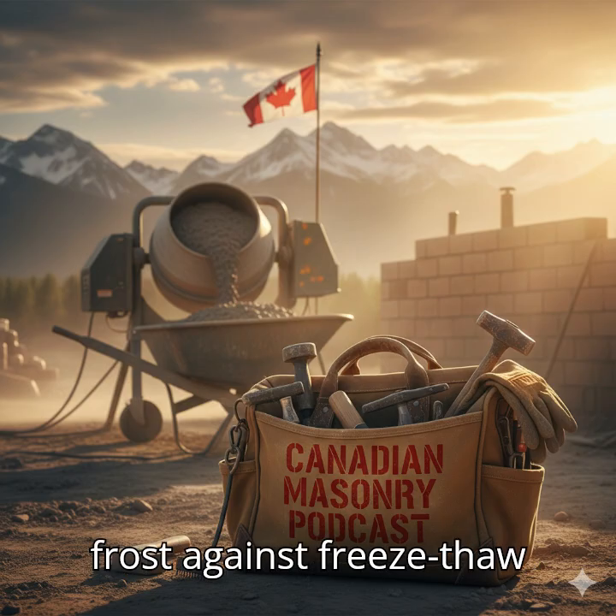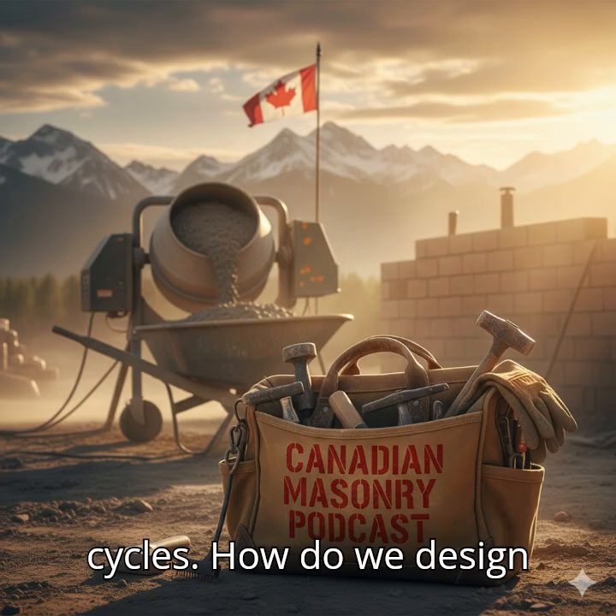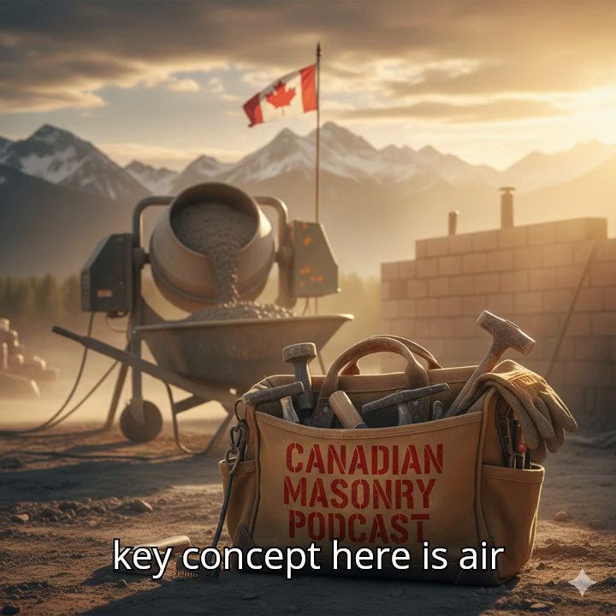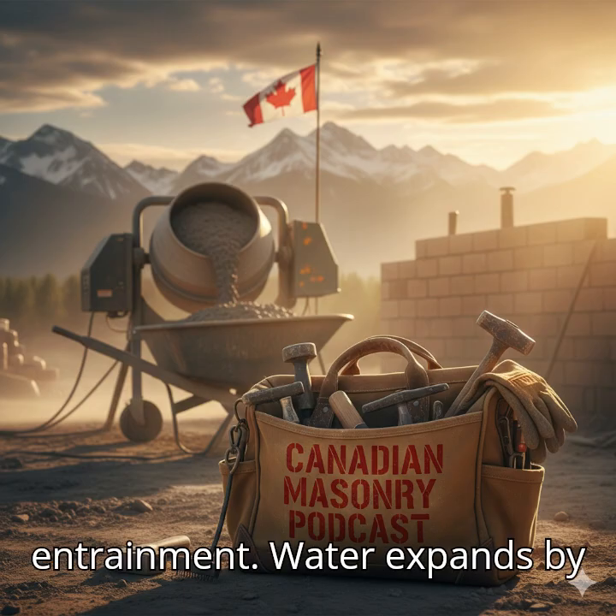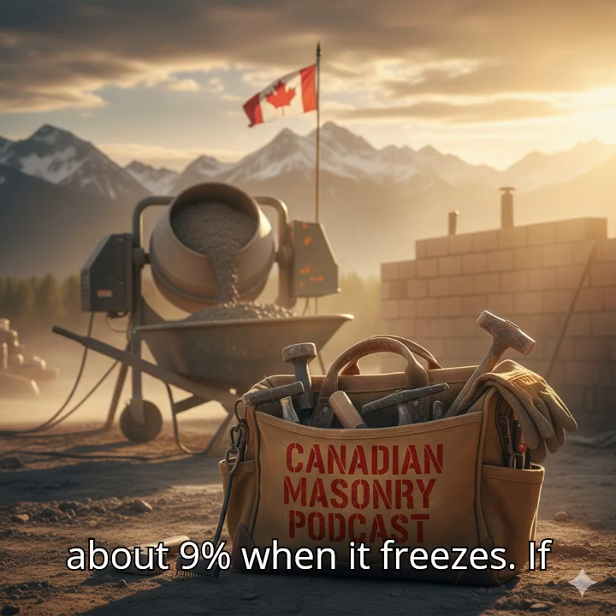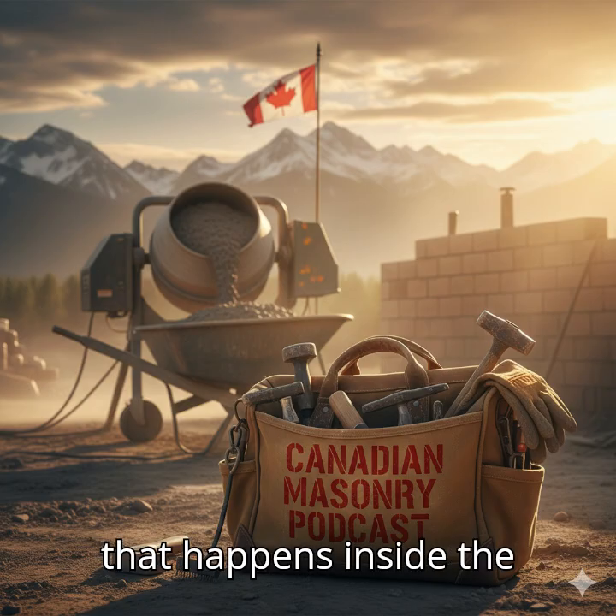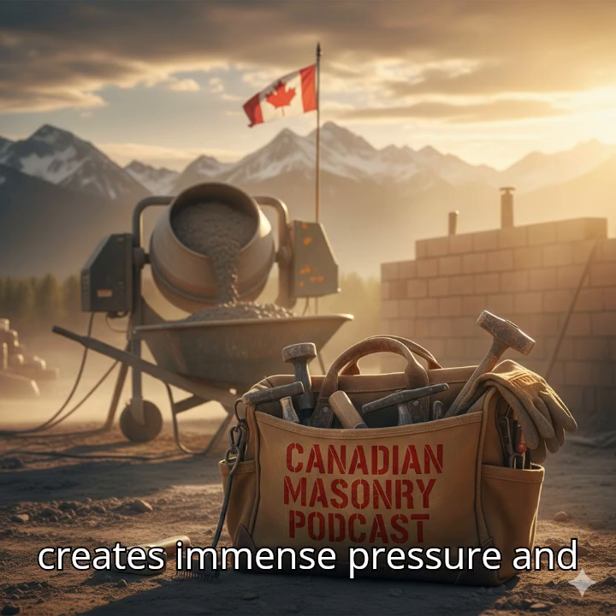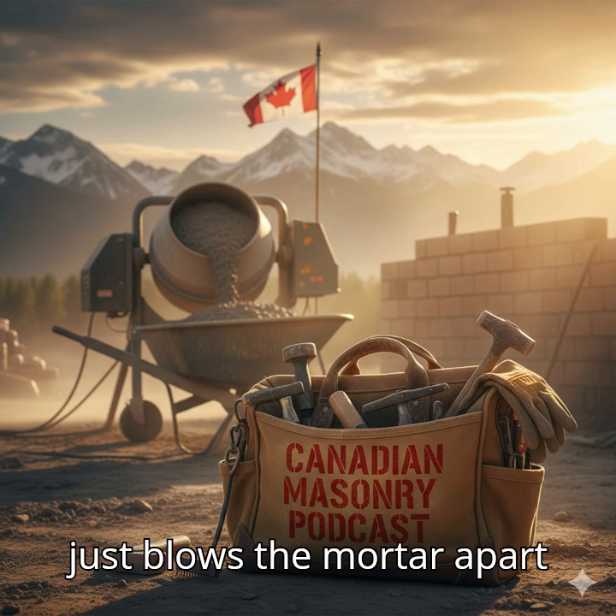Durability against frost, against freeze-thaw cycles. How do we design mortar to survive that? The key concept here is air entrainment. Water expands by about 9% when it freezes. If that happens inside the mortar, that expansion creates immense pressure and just blows the mortar apart from the inside.